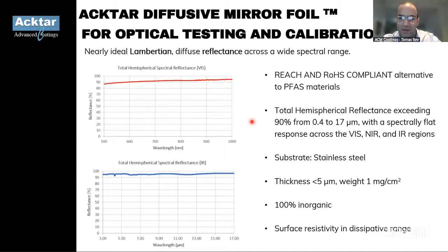The coating itself is deposited on a stainless steel foil. The thickness of the coating is less than 5 microns, and the weight is 1 milligram per square centimeter. Nonetheless, I have to say that all of our coatings are 100% inorganic, just as this diffusive mirror foil and Actar Core Black as well. And in terms of electrostatic discharge, it is ESD safe, and the surface resistivity is in the dissipative range.